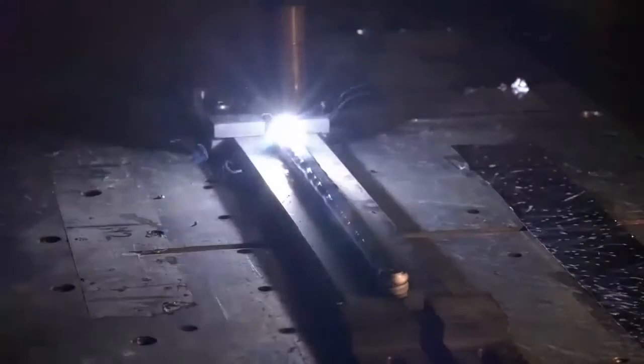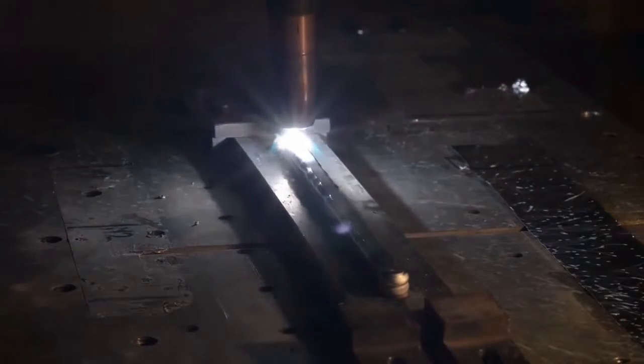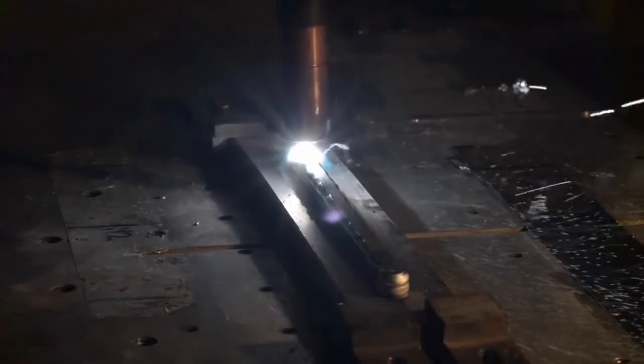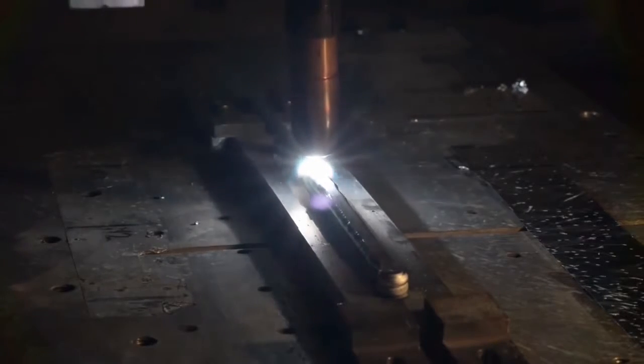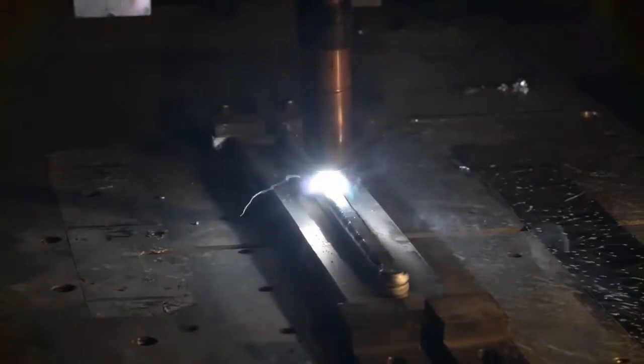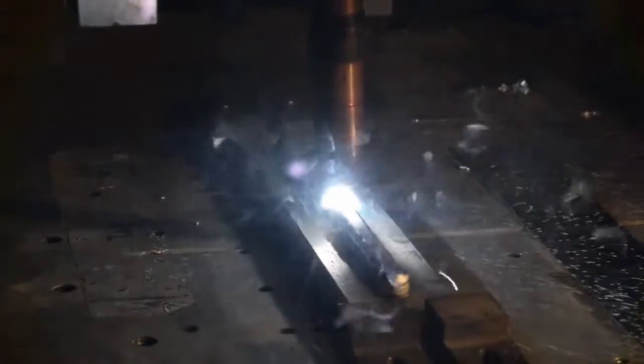components for engineering applications. Another variation is to use a process called wire-based additive manufacturing, where we use a conventional welding process, feed a titanium wire, melt the titanium wire, and then build up a component using welding. And this is what it looks like. So you can see the welding torch over there, and we're depositing layers of titanium metal. This process is much better for producing big components. It's much faster. You deposit a lot more metal in a short time.